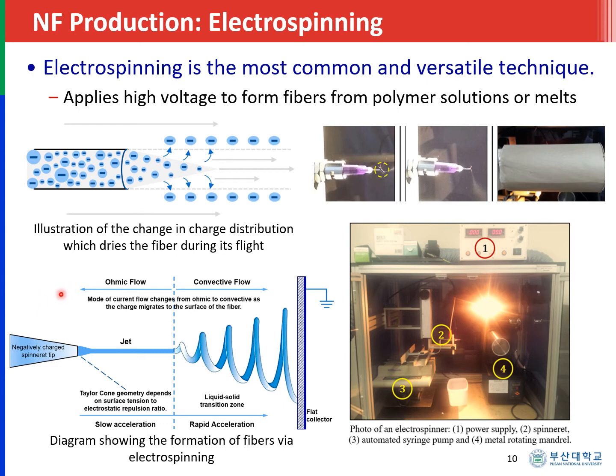If you magnify the polymer solution that is charged with high voltage, then this is what is happening at the tip of the spinneret. The polymer molecules become negatively charged, and they will experience repulsive forces. And due to repulsion, as they travel from the tip going to the collector, they will separate. The solvent molecules will start evaporating, and also the charged jet of the solution will separate into fibers because the polymers are experiencing high repulsion due to the negative charges. So they will repel each other, and they will form nanofibers.